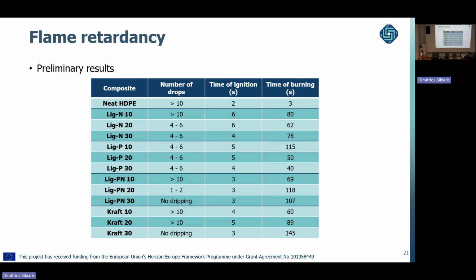So we can see that compared to neat HDPE, most composites have an improved performance because we have less dripping and a larger time for ignition and a longer burning time. And overall, probably the phosphorus and nitrogen modified lignin shows the highest potential with almost no dripping when 30% of additive is incorporated in the composite materials.